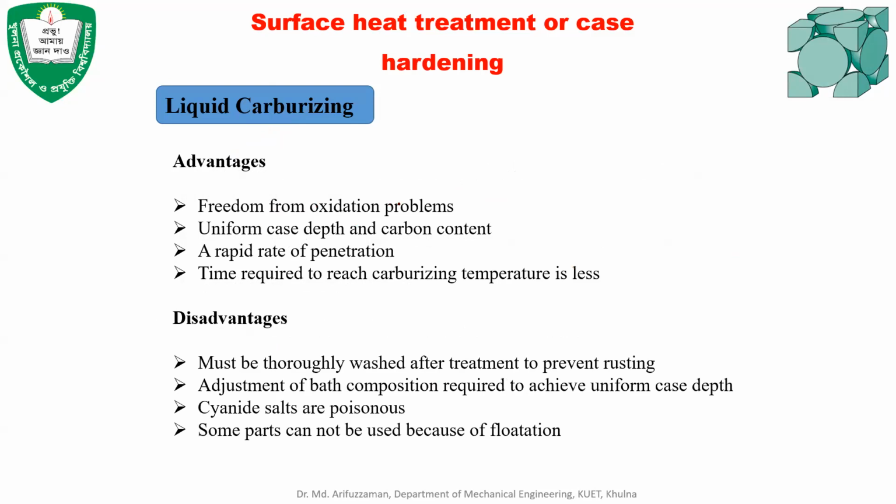Advantages: freedom from oxidation problems, so there is no oxidation issue. Uniform case depth, and carbon content can be very easily controlled, and rapid rate of penetration. The time to reach the carburizing temperature is also less because liquid cyanide can be heated up very quickly.